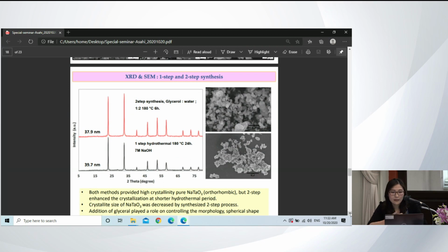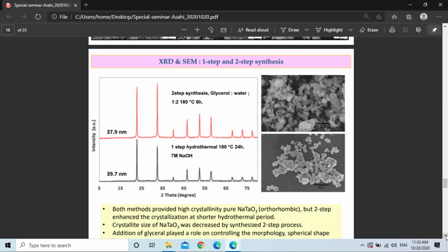So we chose this sample for further investigation by comparing the results of one step and two step. We can see that the XRD patterns show the same crystallinity, but when we calculate the crystallite size by the Scherrer equation, a slight decrease of the particle size was obtained when we use the two-step synthesis.